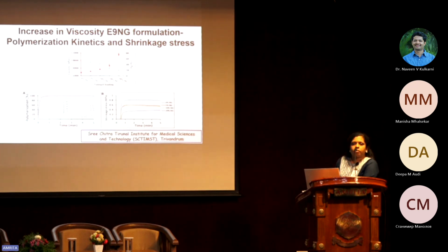And we checked the viscosity of the formulation with different nanogel concentration before curing, and it shows that as the nanogel concentration increases, the viscosity is also increasing, and the TG value of the film after curing is decreasing. So actually, in the acrylic polymeric system, the percentage polymerization kinetics plays a huge role. So we check the percentage polymerization of each film before and after the nanogel loading. The graph shows that the base polymer matrix has about 80 percent conversion within 30 seconds, but as the concentration of nanogel increases, it goes up to 100 percent polymerization.